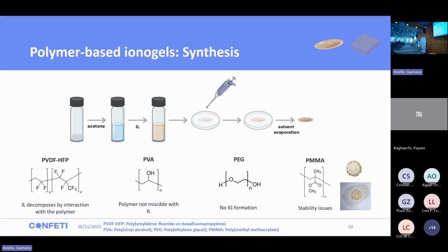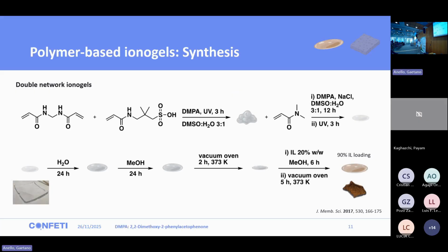So we decided to move to another strategy that was to use double network ion gels. To obtain these materials, we used two different photopolymerizations. The first with an ionizable monomer to increase the affinity between the polymer and the ionic liquid, and a second photopolymerization with acrylamide to improve the physical properties. Then, after some solvent exchange, we can achieve 90% loading of the ionic liquid inside the material.